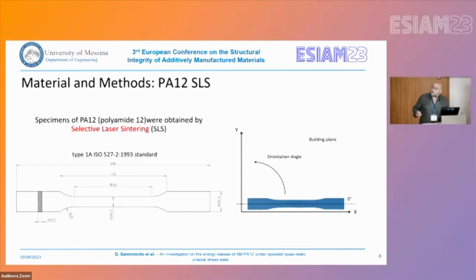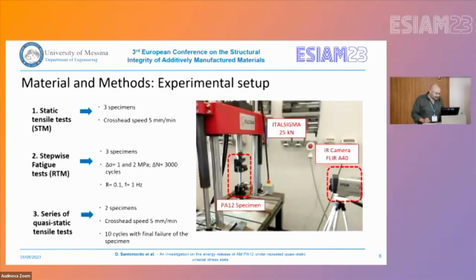We created some specimens according to the ISO standard, and the specimens are produced with an orientation angle of 0 degrees with respect to the x-axis of the building plane. Regarding the experimental setup, we have a servo-hydraulic testing machine of 25 kilonewton maximum capacity and an infrared camera, FLIR A40. We perform 3 kinds of tests.